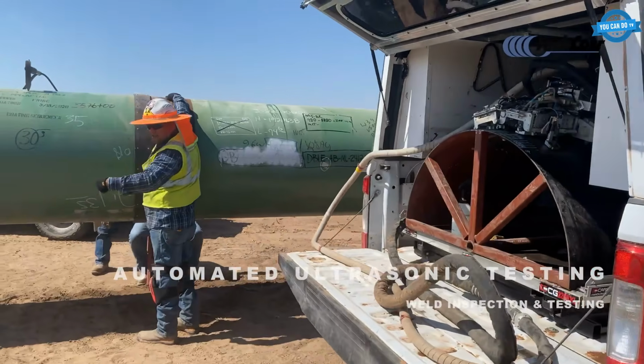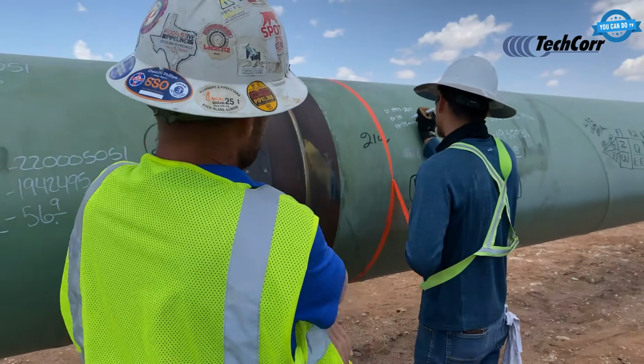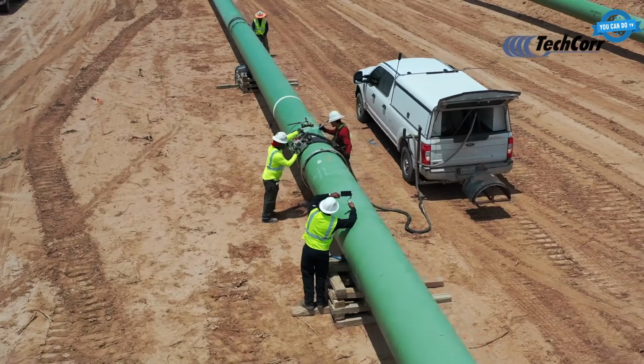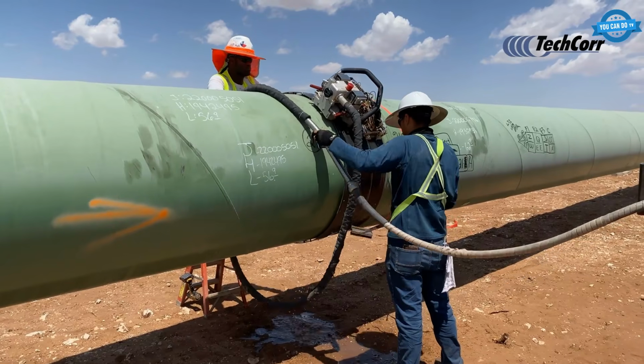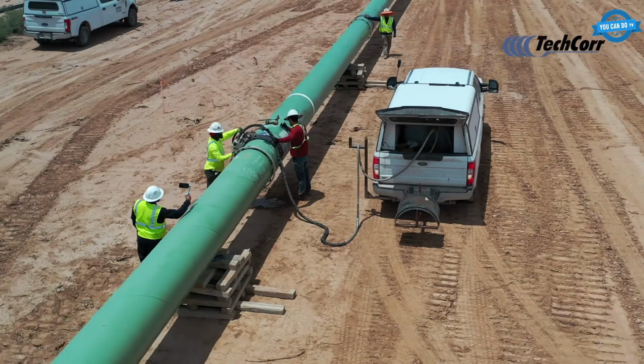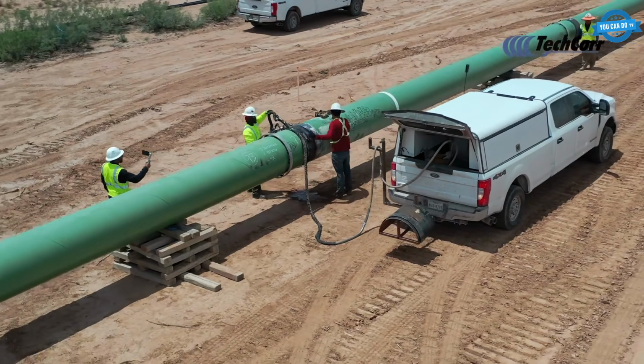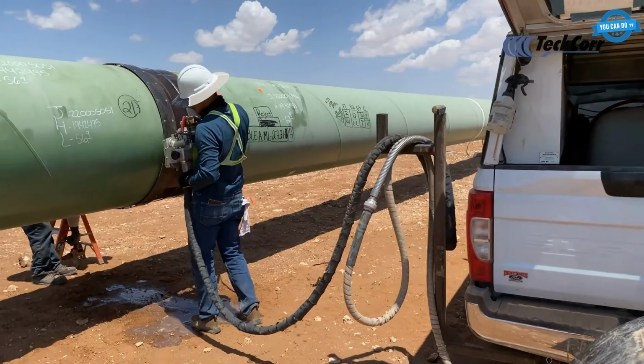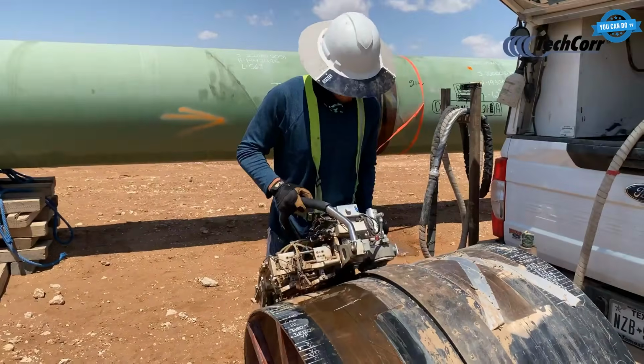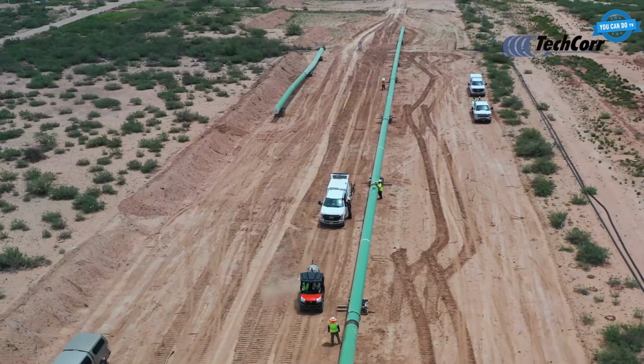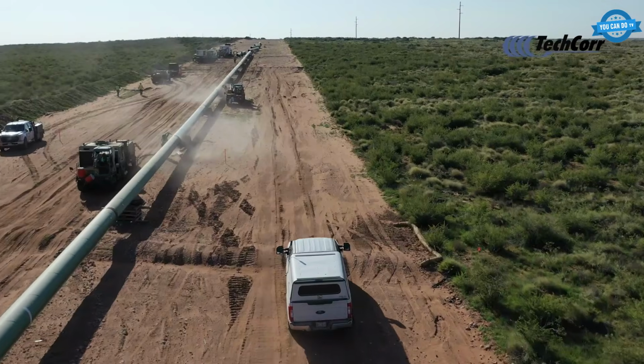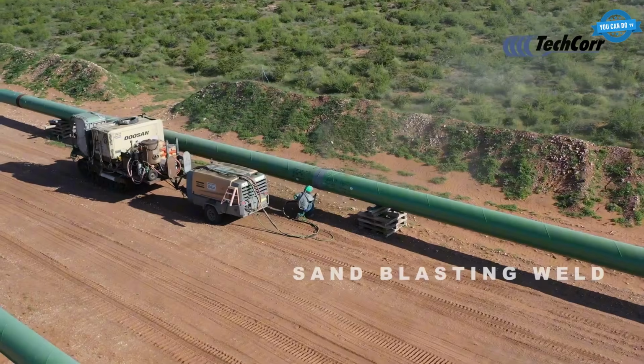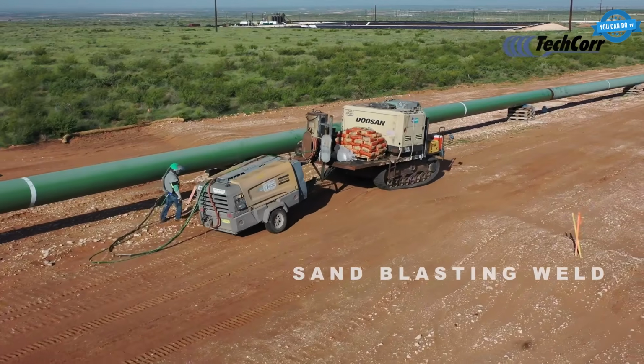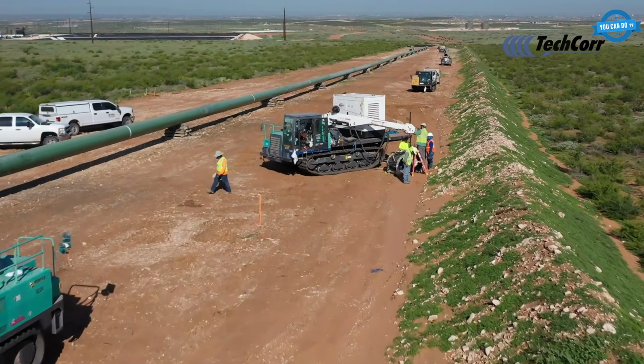The second method is automated ultrasonic testing. A motorized scanner ring wraps around the outside of the pipe at the joint and rotates a full 360 degrees, sending ultrasonic pulses through the weld material. The system measures the echo from any internal flaw and records its size and depth with millimeter accuracy.